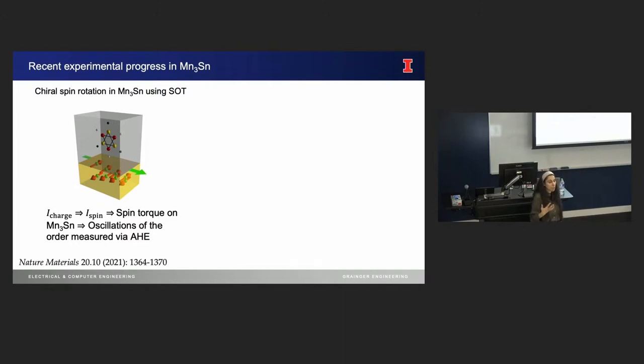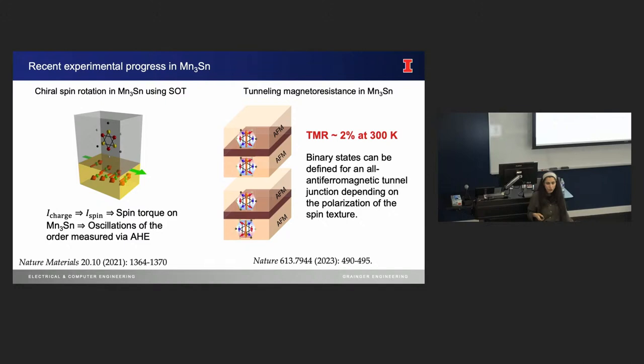So at the time, we were building models. So this was one of the papers that we referred to for validating some of the work that we were doing at the time. And in fact, just a month ago, a new paper has come out in Nature which shows that one could build these tunnel junctions. So you have two antiferromagnetic electrodes with MgO in between. And depending on the relative orientation of the two antiferromagnetic electrodes, you could measure a magnetoresistance, about 2%. You might think it's so small. Well, it's better than zero. Previously, we had nothing. Now we have 2%. So hopefully, we will get better and better as time goes by.